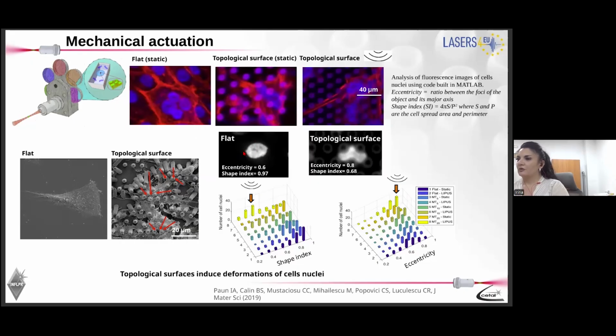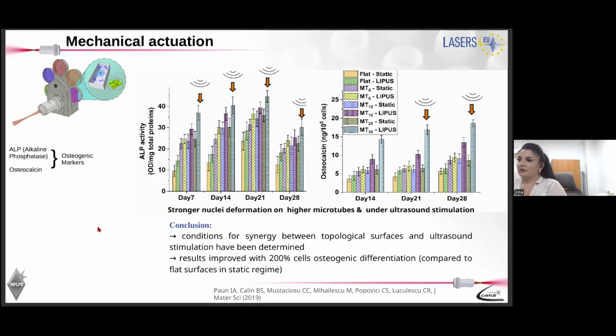Look here first. We compare the shape of a nucleus on a flat substrate versus a nucleus, as I told you earlier, on a topological surface. We had two parameters that enabled us to measure and quantify the shape of the cellular nuclei. And the conclusion was that, you can see here, the highest microtubes that were also subjected to mechanical stimulation underwent the stronger nucleus deformation effects.